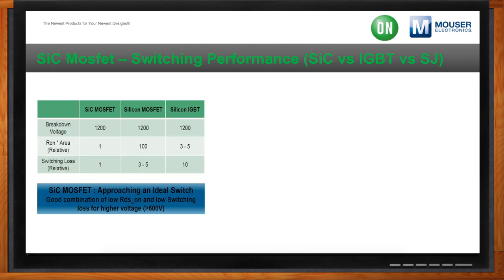I like to start off with this little diagram on the left here, and it shows the differences between your silicon carbide, your silicon, and your IGBTs. If you take a silicon carbide MOSFET and compare everything to it, a silicon MOSFET has an RDS on area that's 100 times bigger, and switching losses are 3 to 5 times bigger. Now, if we look at an IGBT, you have a die size area 3 to 5 times bigger with a switching loss of 10 times bigger. So silicon carbide MOSFETs are really approaching an ideal switch. They have a good combination of low RDS on and low switching.